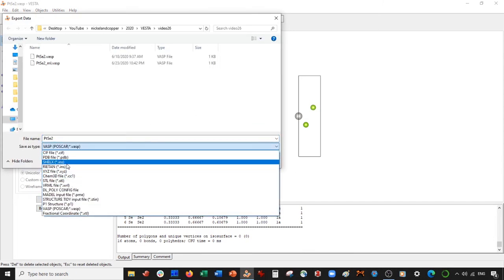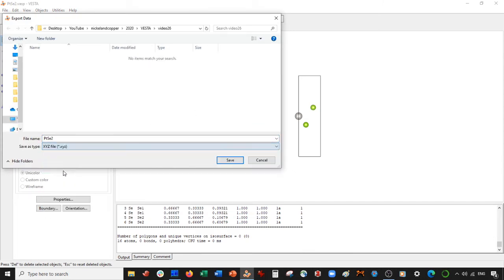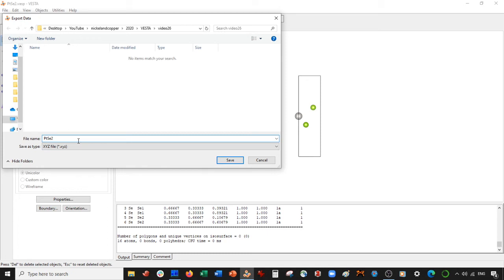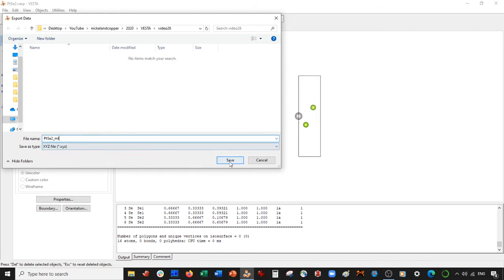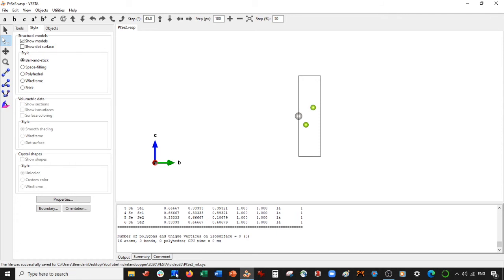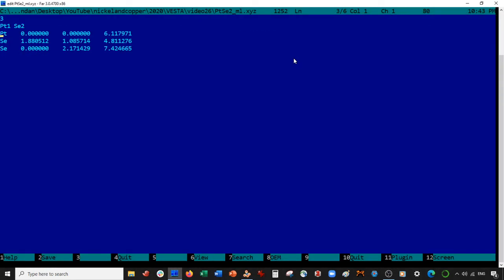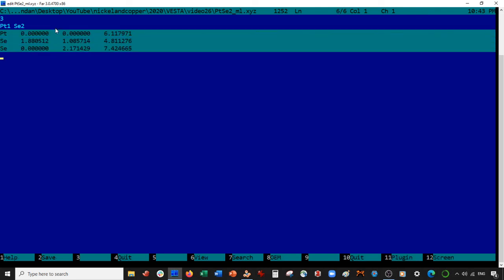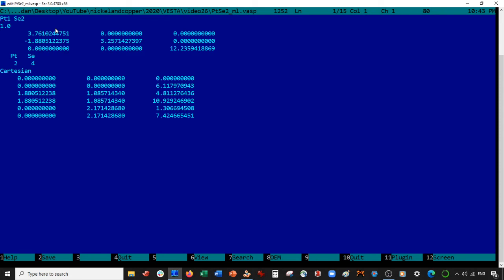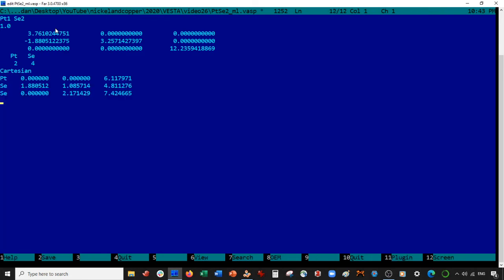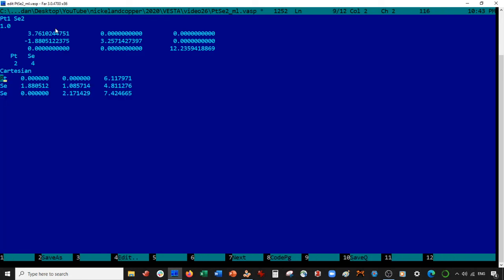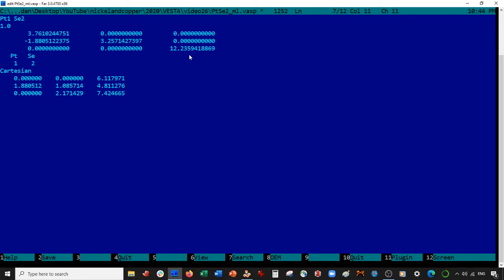Then we're going to save this file, export data as an XYZ. Platinum selenide monolayer dot XYZ. For some reason when I save it as a VASP, I have to save it literally as dot VASP, even though I save as type VASP. But for XYZ, I don't have to do the dot XYZ explicitly. Now we go to our platinum selenide monolayer XYZ and you can see we have this one platinum, two selenide stoichiometry preserved. I'm going to copy this into the monolayer VASP file. Since we only have one platinum followed by two selenium, we have to reflect that here. The first atom is platinum, the next two are selenium.